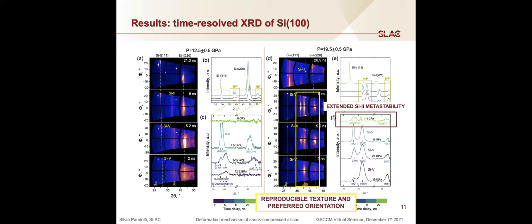And another, the most interesting thing, I think, is that we did observe a very reproducible preferred orientation for which the 001 and 010 reflections of the silicon 5 high pressure phase were always at the same azimuthal angle as the 220 reflection of silicon 1.